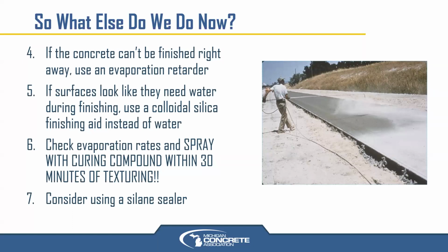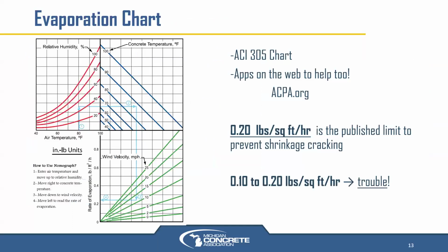There are some cure and seal combo products out there that are sprayed on in the curing compound side of things. As far as within 30 minutes, it's half curing, half silane sealer. Those are fine. They're just half as good as a full coat of curing compound, and half as good as a full sealer applied at a later age, but it's better than nothing. So those in general are our recommendations. There are lots of other products and chemicals out there that could work as well.